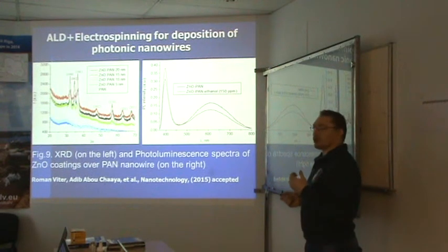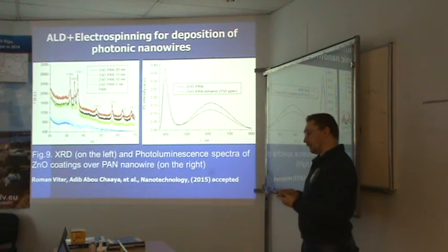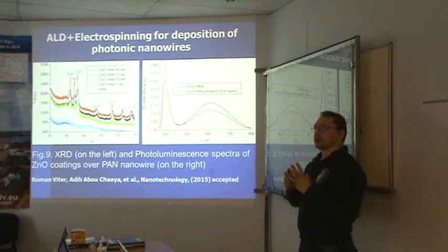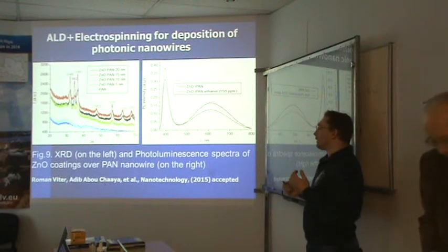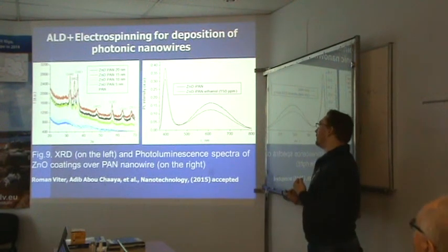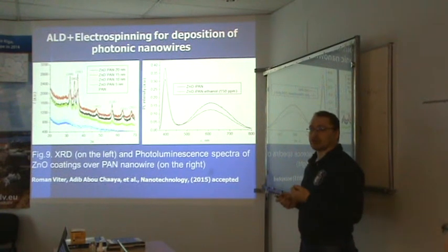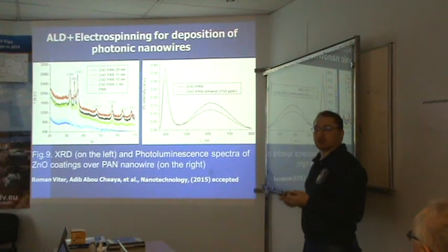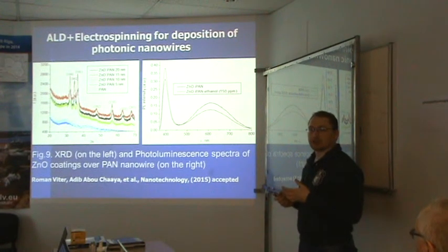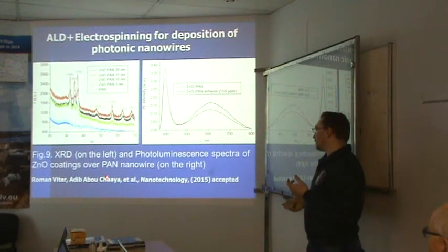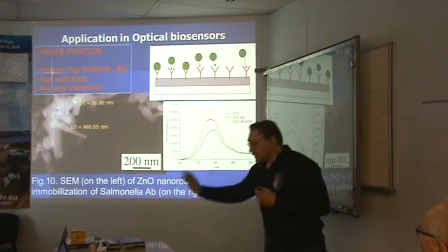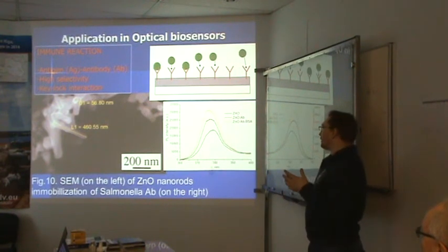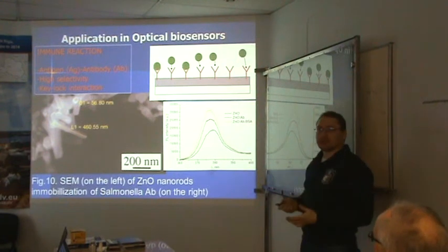And then we showed the practical applications of these nanocomposites for gas sensing. We put this structure into the chamber, and we exposed it to 150 ppm of ethanol, and in this figure you can see the changes of the photoluminescence versus ethanol concentration. Of course, this is the first step, and we will continue our work and try to make calibration versus the concentration. The next step is the application of these nanostructures in biosensors and bioapplications.